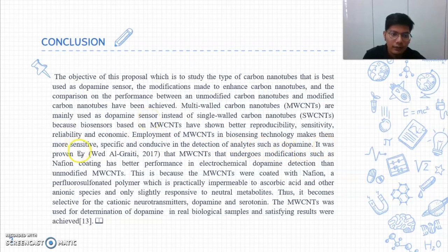It was proven by the article by Wed Al-Graiti 2017 that multi-wall carbon nanotubes that undergo modification such as Nafion coating have better performance in electrochemical dopamine detection than unmodified multi-wall carbon nanotubes. This is because the multi-wall carbon nanotubes were coated with Nafion, a perfluorosulfonated polymer which is practically impermeable to ascorbic acid and other anionic species, and only slightly responsive to neutral metabolites. Thus it becomes selective for the cationic neurotransmitters dopamine and serotonin.